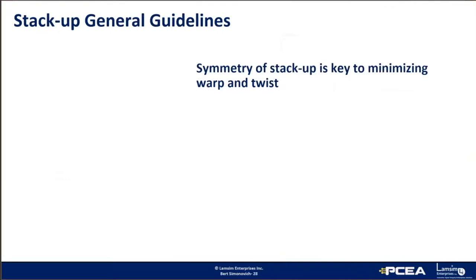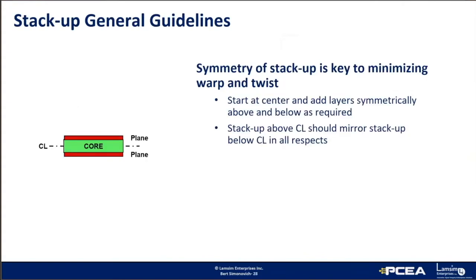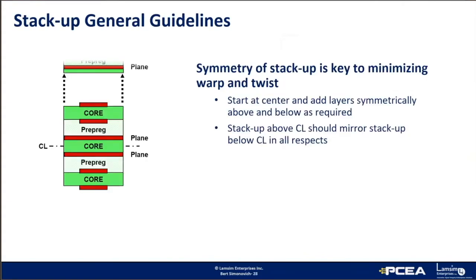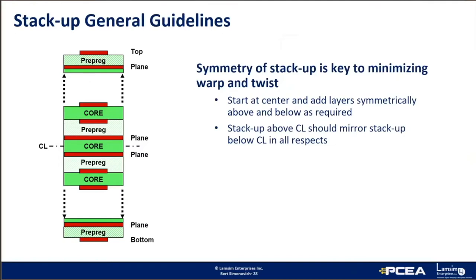When building a stack up, symmetry is key to minimizing warp and twist. If we start at the center with a double-sided core, we add layers symmetrically above and below the center line. We continue this process until the desired number of layers is reached. It is most common to have a prepreg layer adjacent to the top and bottom of the board. And because of this, the center layer might start off as a prepreg to ensure the stack up ends with a prepreg at the top and the bottom.